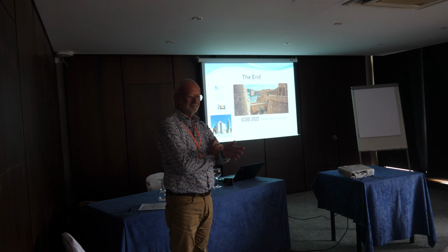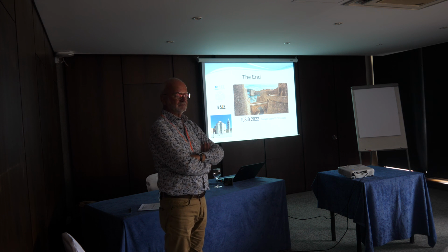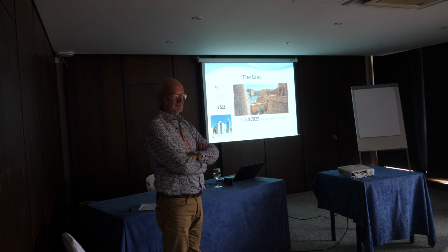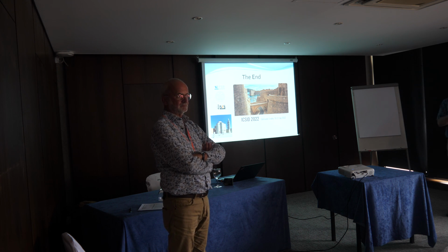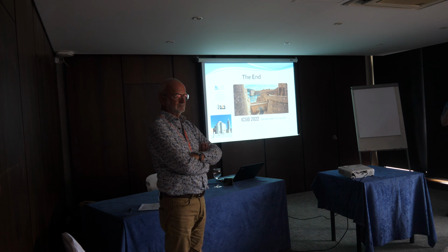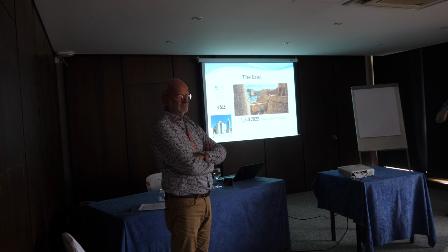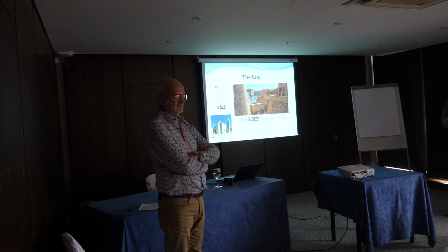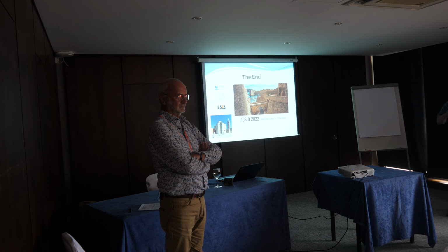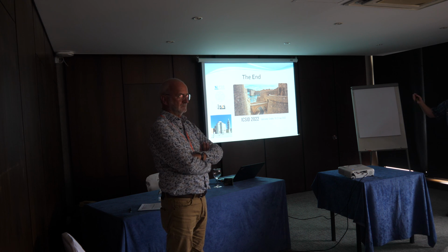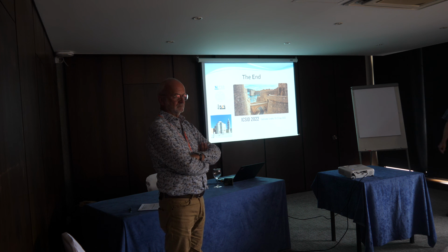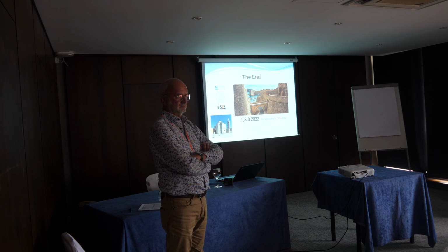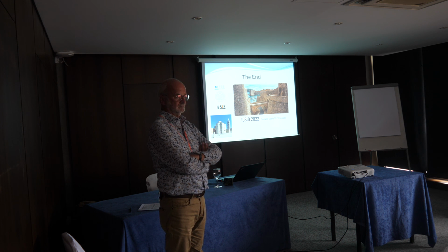Only to make it clear, you didn't simulate the corrosion. No. We take specimens, then we modeled using a Poisson stochastic process distribution over the surface. So it was like a roughness. Yes. But of different size and depth, and after that, ANSYS and LS-DYNA, and we get this result. But corrosion as a process, that wasn't modeled. That's another story.